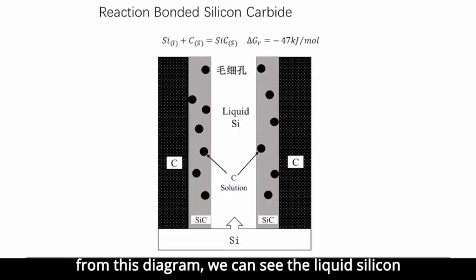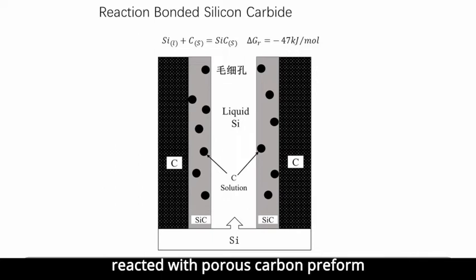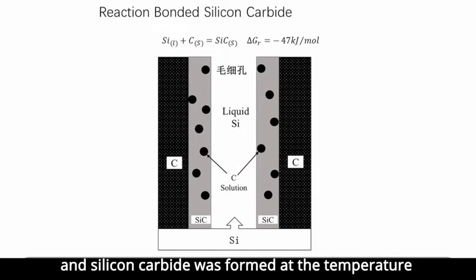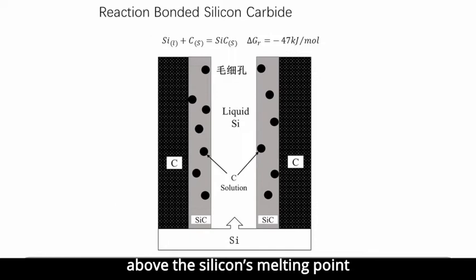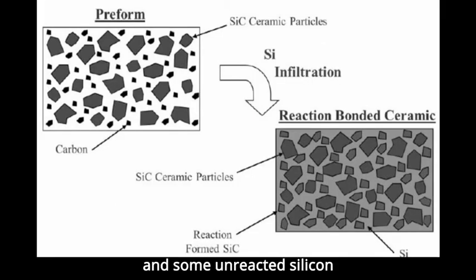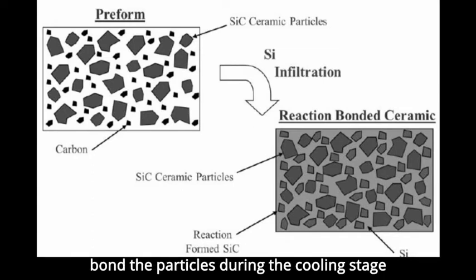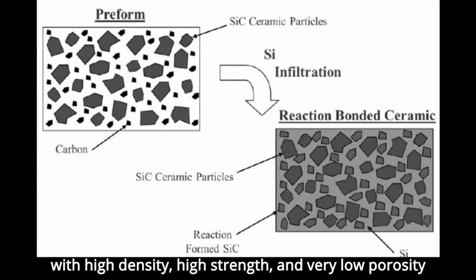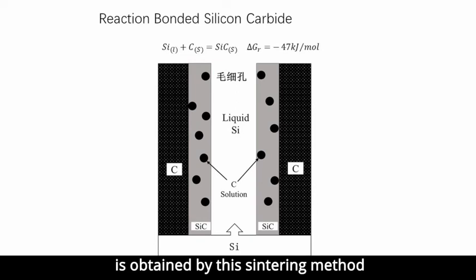From this diagram, we can see the liquid silicon reacting with the porous carbon preform, and the silicon carbide is formed at a temperature above the silicon's melting point. The newly reaction-formed silicon carbide, and some unreacted silicon, bound the particles during the cooling stage. As a result, a dense silicon carbide ceramic with high density, high strength, and very low porosity is obtained by this sintering method.